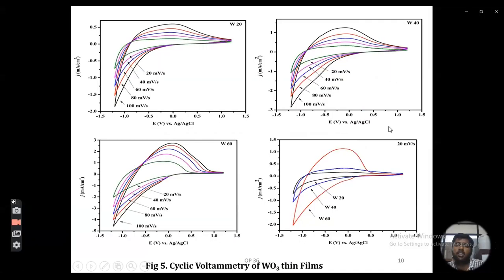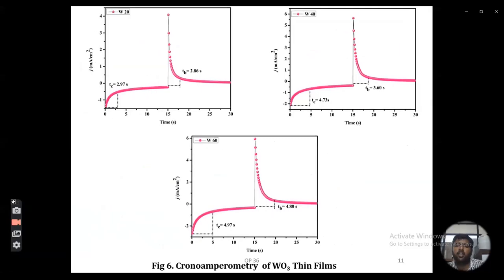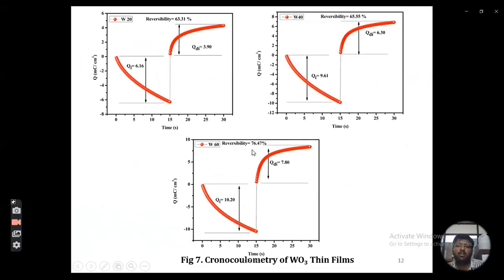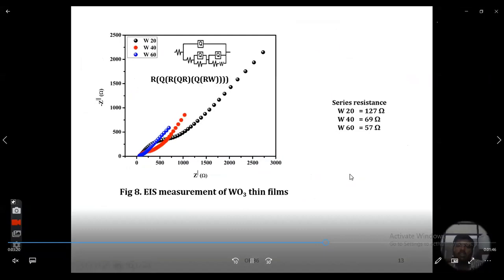In order to study the electrochemical properties, cyclic voltammetry was carried out for each sample at different scan rates. Then chronoamperometry and chronocoulometry were carried out to study the reversibility, charge insertion, as well as coloration and bleaching step timing of the WO3 thin film at -1.2 volt and +1.2 volt for 15 seconds each, which gives the higher reversibility of 76.47 for the W60 thin film.